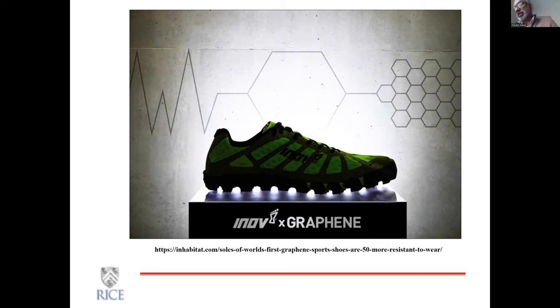What you said is an interesting thing to say about 2D materials. Many of these structures like molybdenum sulfide, people consider very low friction, but it's not always the case, because there are many other parameters in friction. Graphite is a good example. Graphite is a poor lubricant in a dry atmosphere, or molybdenum sulfide gets oxidized very easily, so they're not very good either. So for friction properties, what you need is a surface that is very stable and smooth, and electronic properties certainly matter, I suppose. So I think this was kind of by chance. Okay. Thank you.